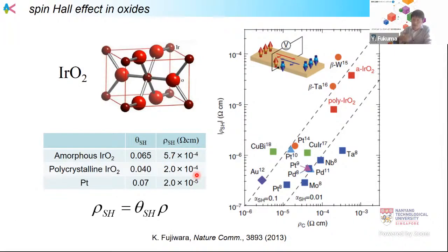That's why, when we consider spin current detection using an electrical signal, for example, if I want to convert the spin current to voltage, this is good. For comparing the conversion efficiency from spin current to charge current, the iridium oxide material shows a similar figure of merit compared to beta tantalum and beta tungsten. Because these materials show higher resistivity, they are good for detection.